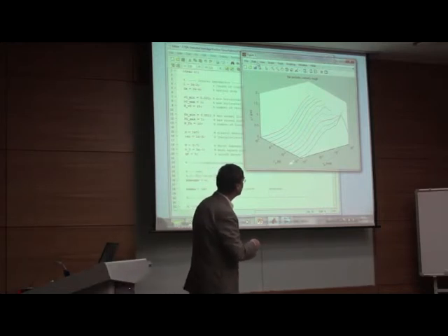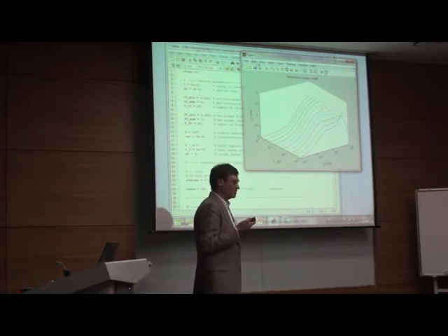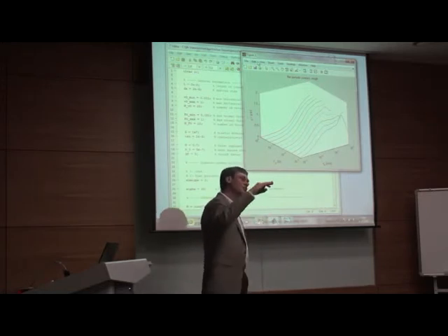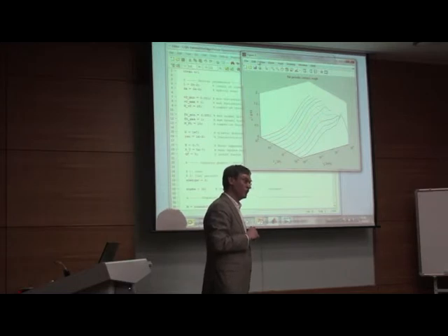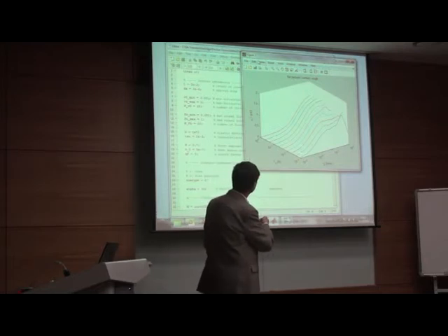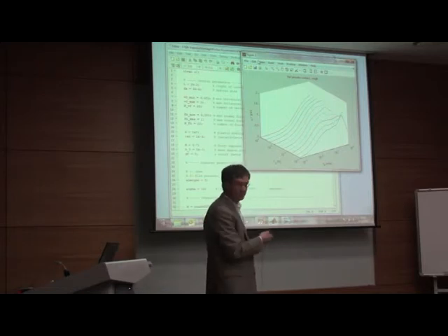So, first of all, as a function of velocity, as theory predicts, so to say, as everybody knows, it will increase with velocity and then come to a plateau for the Kelvin body. And you see something like this, but it also depends on the force. This is small force, this is large force, the ratio is 10 to the power 3. And then, for example, if you are here on the plateau, then you have almost no dependence on the force. If you are here, then you have dependence on the force.